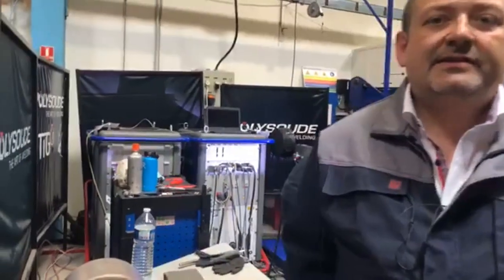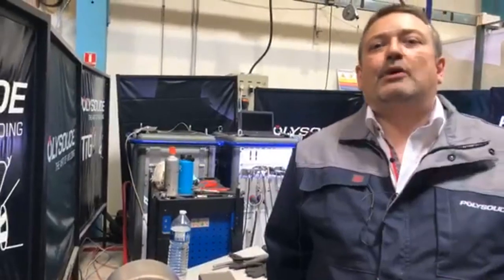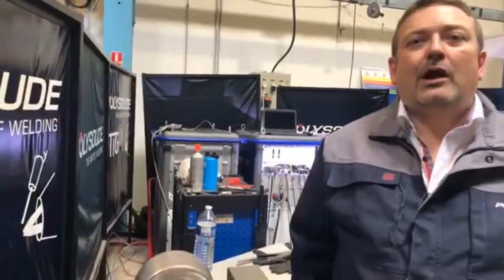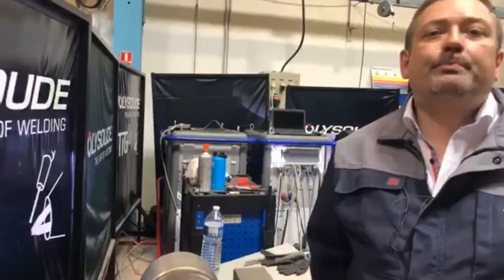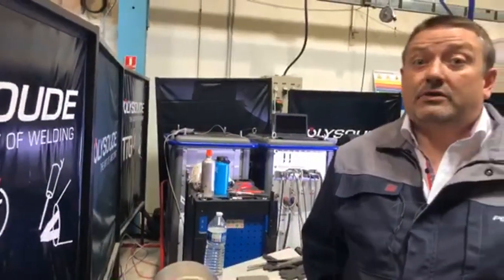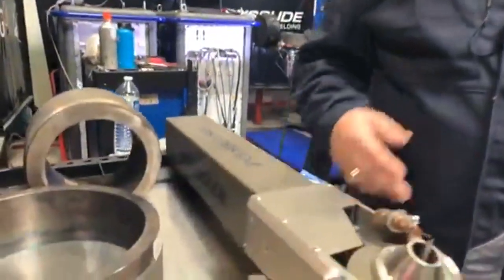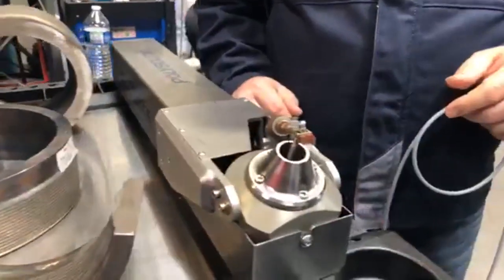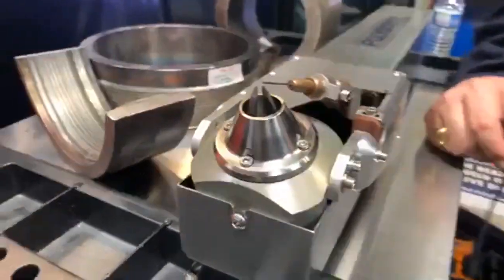We found out by experimenting that there are some magnetic effects that reduce the arc pressure. And of course, when you weld, you are looking for arc pressure to get a good penetration. In our case, using the two electrodes, we didn't have that arc pressure. And somebody said, oh, but if the heat is not pushing on the inside, this is perfect for the cladding, because you want to be as cold as possible in order to avoid and to limit the dilution of your ferrite in your Inconel. And that's how all the story has started, by using two cathodes for the TIG application.